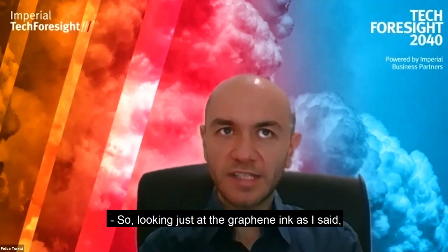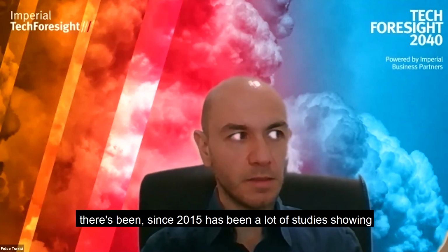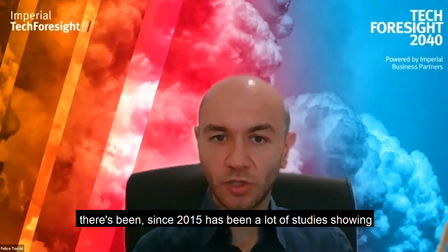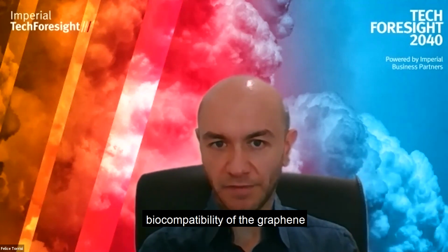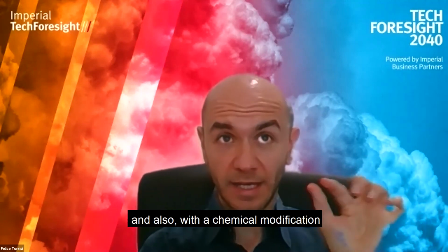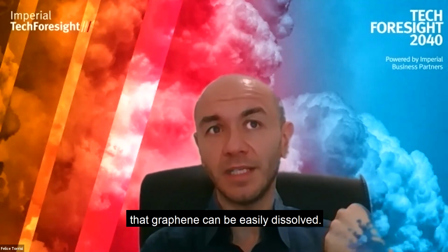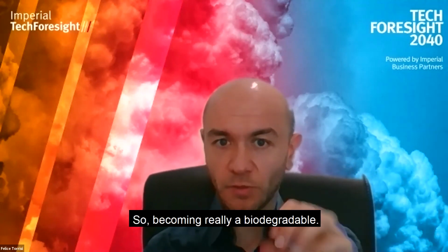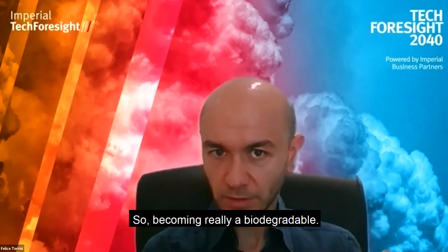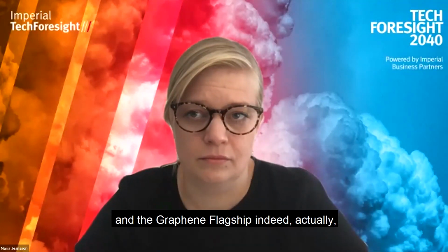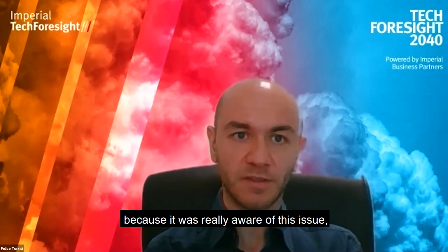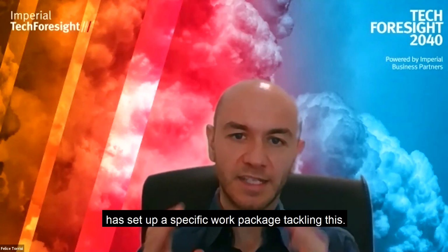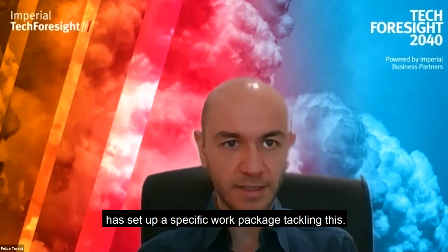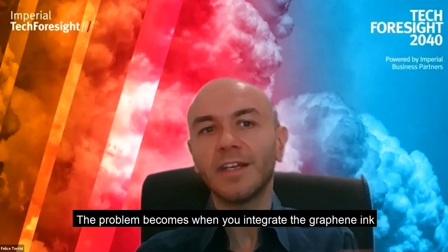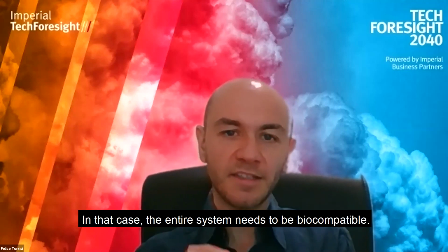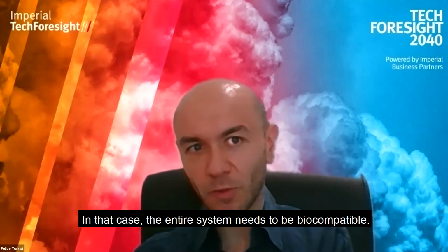So looking just at the graphene ink, as I said, since 2015 there have been a lot of studies showing biocompatibility of the graphene, and also with a chemical modification, graphene can be easily dissolved, so becoming really biodegradable. There have been a lot of examples for this, and the Graphene Flagship, because it was really aware of this issue, has set up a specific work package tackling this. The problem becomes when you integrate the graphene ink with your textile.